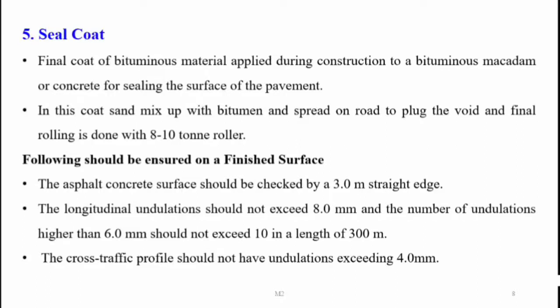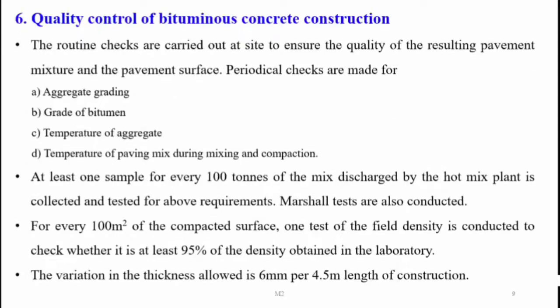Once the seal coat is complete, the finished surface is checked using a 3-meter straight edge to ensure quality. The longitudinal undulation should not exceed 8 mm, and the number of undulations higher than 6 mm should not exceed 10 in a length of 300 meters. The cross traffic profile should not have undulations exceeding 4 mm.